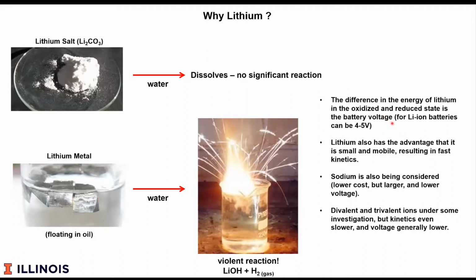And so it's very important that you have a high voltage battery. And for lithium-ion batteries, the difference in the potential of the lithium is between 4 and 5 volts, depending on the details of the materials you pick. You'll actually see in the literature a large number of reports saying things like high capacity battery, fast charging battery, or high power battery. In many cases, those are much lower voltage systems. So while they may store a lot of ions and they may be able to move those ions quickly, if the voltage is lower, the overall energy of the battery is suppressed substantially.